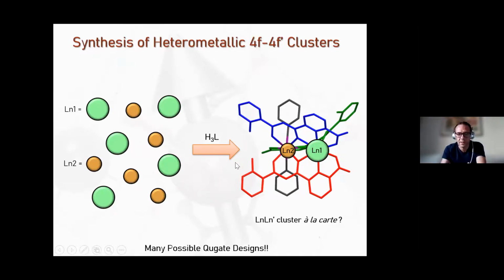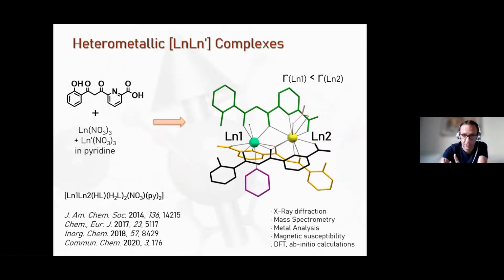So this, in fact, is a coordination system that offers this wonderful possibility, and it works remarkably well. We've produced many different systems and studied them from various points of view, and used a large array of techniques that allow us to say that for many combinations, this selectivity is very high. It becomes a bit smaller as the metals become closer in size. And we've realized, especially through mass spectrometry and also confirmed by calculations, that when we move from the solid state to solution, this selectivity decreases a little bit.